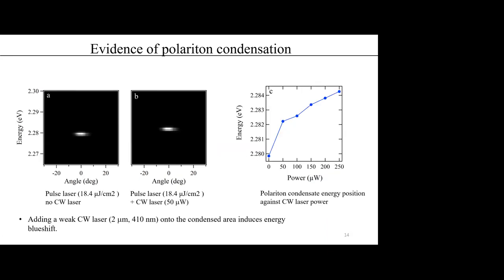Secondly, we also check whether polariton condensation occurs or not in the strong coupling regime by another method. Here we add a very weak CW laser, which is focused onto the center of the femtosecond laser, where we observe polariton condensation. In this case, the interaction between the injected exciton reservoir by the CW laser and the polariton condensate created by the femtosecond laser can induce noticeable energy blue shift.